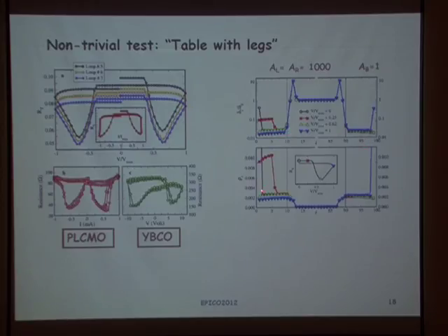So when we observe the resistivity along the sample in the low resistance state, we see that the local resistivity diminishes at both interfaces, and as we add up all the resistances, we have the two-terminal resistance that gives rise to the low resistance state. In the same way, we can follow and characterize the different vacancy profiles with the profile of resistivities along the sample as we increase the voltage.